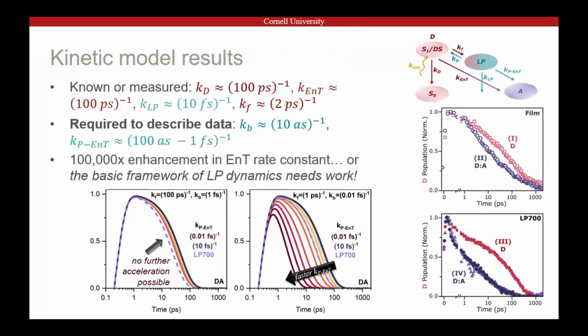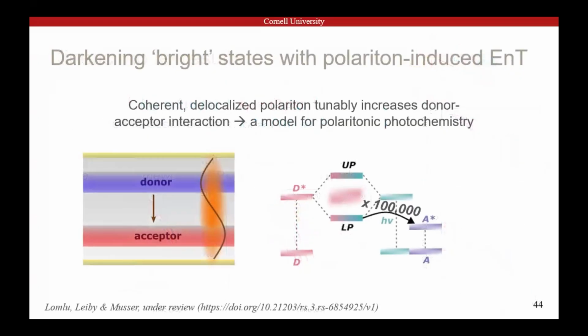Basically, the back transfer from polaritons back to the dark states has to be in the attosecond regime. The polaritonic enhanced energy transfer can be no slower than a femtosecond to describe our observations, which means that strong coupling is actually enhancing this donor-acceptor transfer by a factor of about 100,000, which starts to be consistent with this very big collective state. It's just there's a faster process of scattering back to the dark states that slows it down. And this tells us the way to improve what polaritons do is to manage this equilibrium. But there is real scope to use polaritons to redirect photophysics.